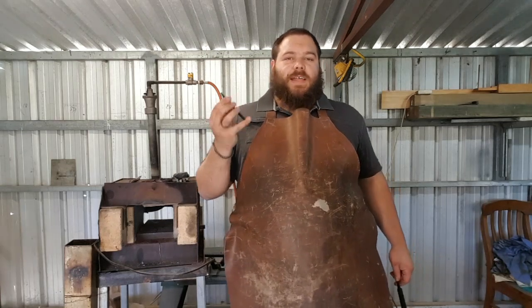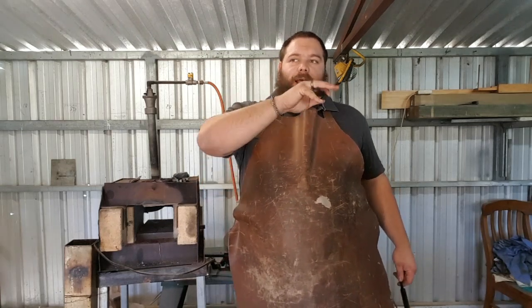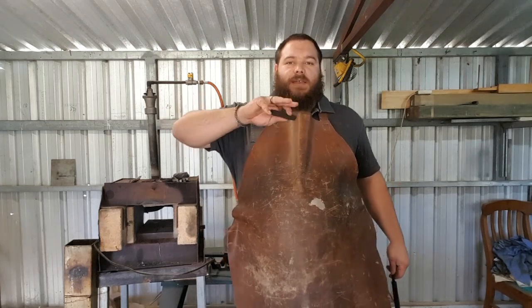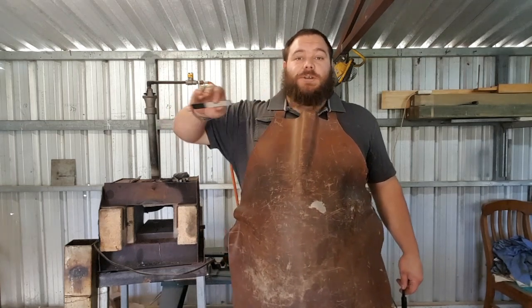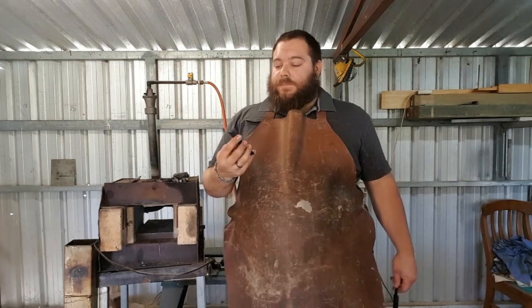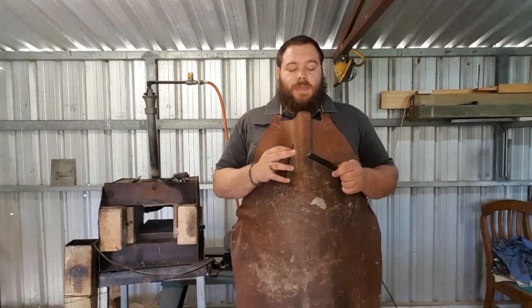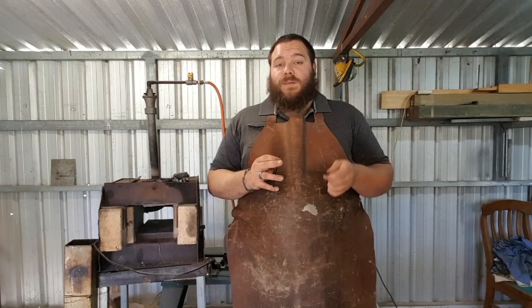The fact is that that's not true. It's just the fact that staying at heat for so long has meant that it's actually developed a thicker oxide layer than it would have otherwise. It's still at the same hardness it was 4.5 hours ago, or it was still the same hardness as it was after the temper had reached the center of the material, which is the other thing about torch temper.